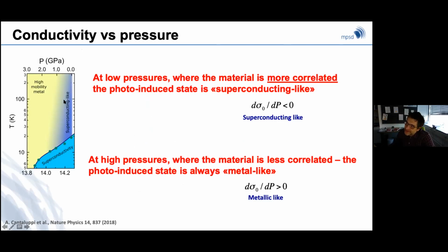So you have this very small sliver of behavior here in the low bandwidth, in the highly correlated side close to the dome, where the response is superconducting-like, that is to say, where the light-induced conductivity gets worse with pressure, the slope, in the same way that this happens at equilibrium. Whereas here, at first sight, maybe if we had known this 5 years ago, we'd have written a paper saying that this yellow side was also a light-induced superconducting-like state.